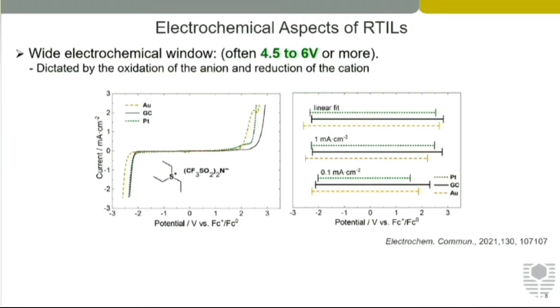From an electrochemical point of view, we need to understand the electrochemical windows of these ionic liquids. An electrochemical window is defined as the operating potential range where there's no current. So if we then want to see an analyte oxidation or reduction, we don't want to have a background here. At the edge of this operating potential window, you'll see a steep rise in the current, both in the negative range and in the positive range. This is the reduction of the cation, and this is the oxidation of the anion.